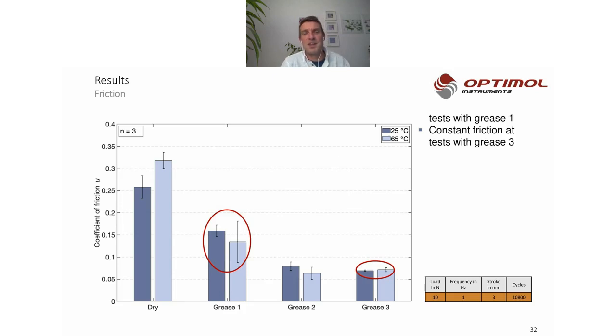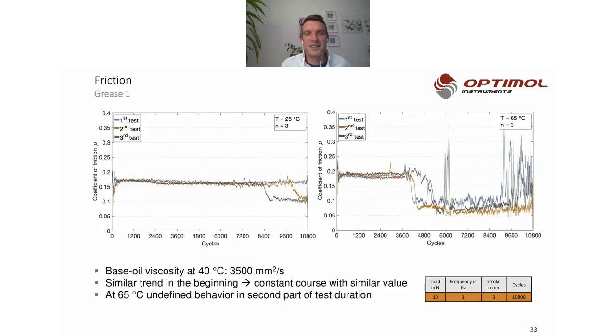And as I already mentioned, the main task was that the friction behavior needs to remain constant over the lifetime. That's why we had a look at the friction data. As you can see on the left side, it's the data for the room temperature test, and on the right side, it's for the high temperature of 65 degrees. And as you can see, the friction level for this grease number 1 is very constant, very smooth, until something happens there. And this behavior even increases or gets more and more critical if you raise the temperature.